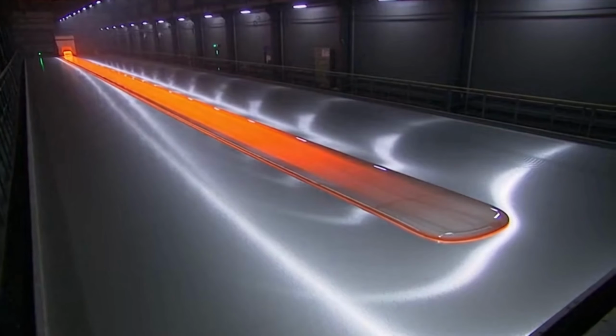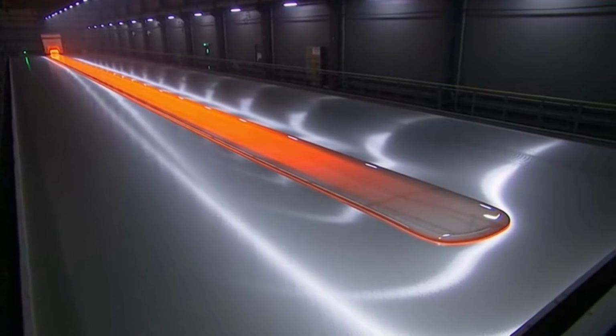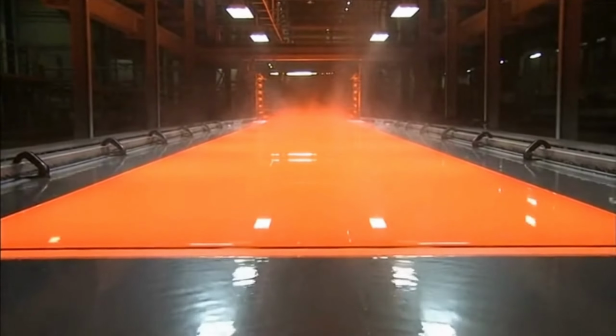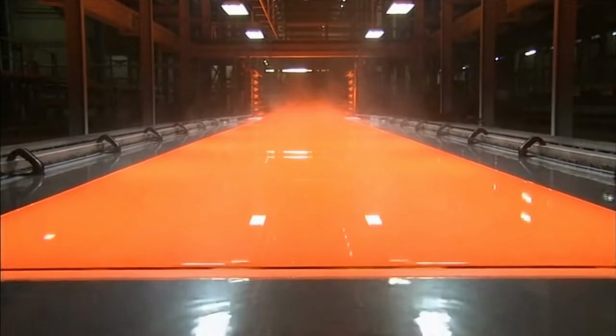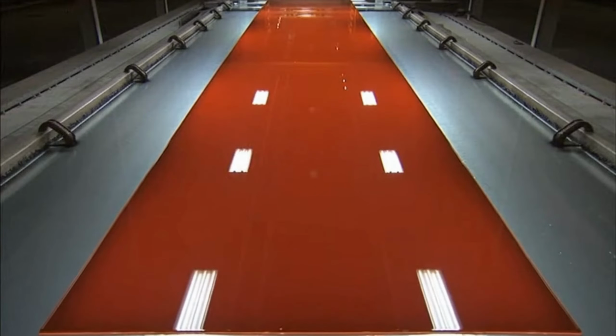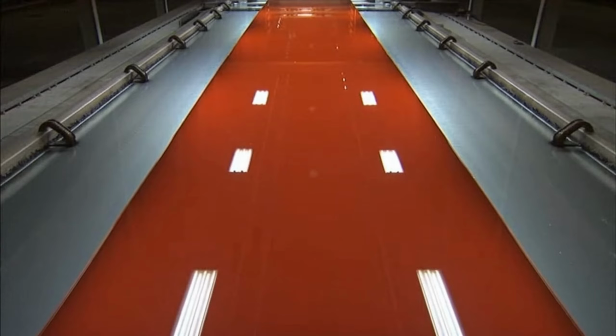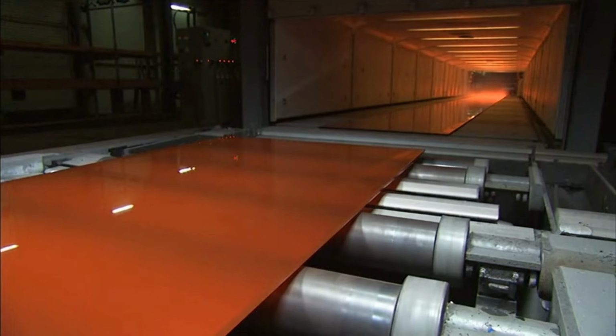Molten glass, still glowing fiercely, is carefully poured onto a bath of liquid tin. Here, it doesn't just cool, it floats. As the glass ribbon extends across the molten tin, it cools, solidifying its pristine flat shape. But the process isn't complete. It then enters the annealing lehr, a controlled cooling tunnel essential for preventing internal stresses and ensuring its strength.